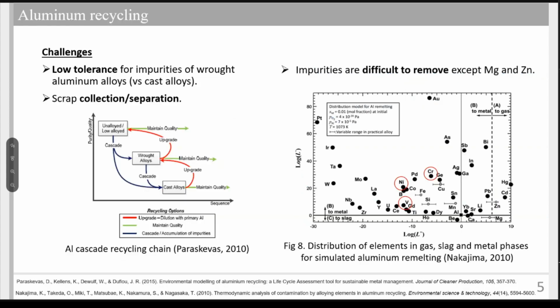Now, aluminum recycling poses its own challenges, most notably the low tolerance of impurities for wrought aluminum alloys compared to cast alloys. Such impurities are difficult to remove. If you look at the three we mentioned, they are much harder to remove compared to, say, magnesium and zinc. And this difficulty will affect the whole scrap collection and separation strategy and the whole aluminum cascade recycling plan.